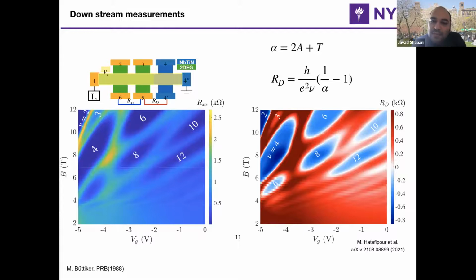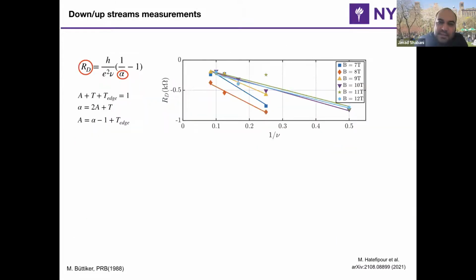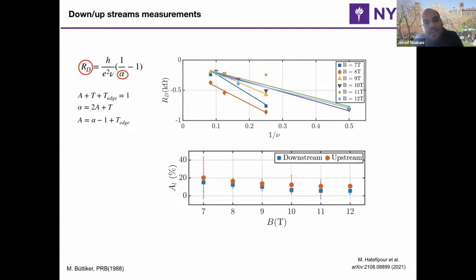8, and 12, right? So for each of these fixed fields, I can try to actually plot the negative values and then ask what is the slope, and the slope should be basically related to alpha, right? And from alpha, I can basically back-calculate a lower bound for the Andreev reflection. And it seems, if we believe in this simple analysis, the Andreev reflection has some field dependence, perhaps, and it sort of varies around 20% down to maybe 10% as the field is increased, right? So this is basically the basic observation.